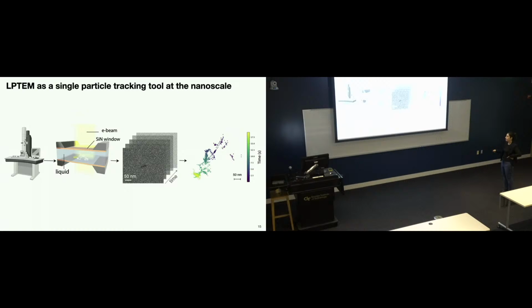So we take the TEM and the commercialized silicon nitride liquid cell E-chips, and we put our nanoparticles, which we synthesize in different shapes, sizes, or surface chemistry, into this solution. Then we collect videos of the motion of these nanoparticles, which we analyze using algorithms that we have developed in our group, and we arrive at spatiotemporal trajectories, which are thousands of coordinate points of the particle in time. And then we start from there to think about what sort of chemistry and physics we can extract from